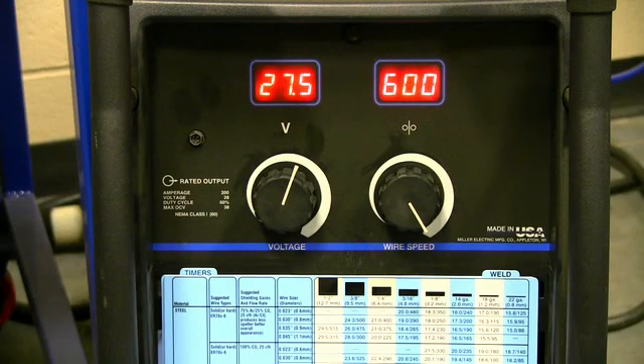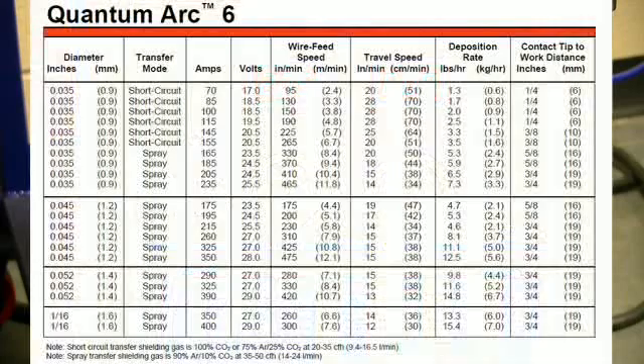So as far as setting the correct welding parameters, I'm going to start at 27.5 volts and 600 inches per minute. I know these are good parameters based on experience, but if you're not sure, the best thing to do is to check with the wire manufacturer's data sheet. This always has a good table for some starting parameters to get started.